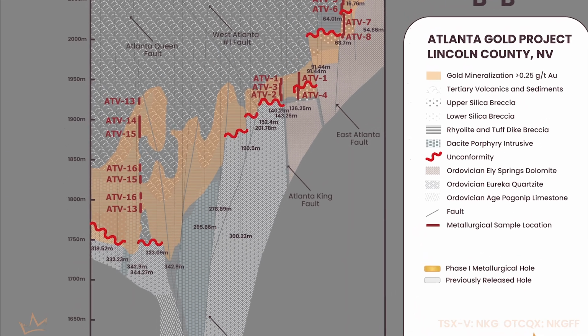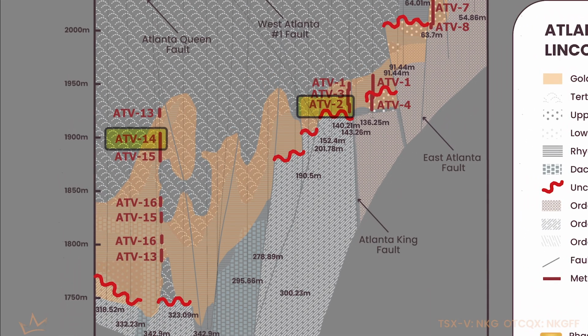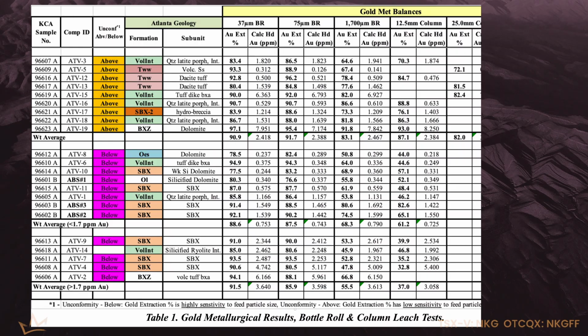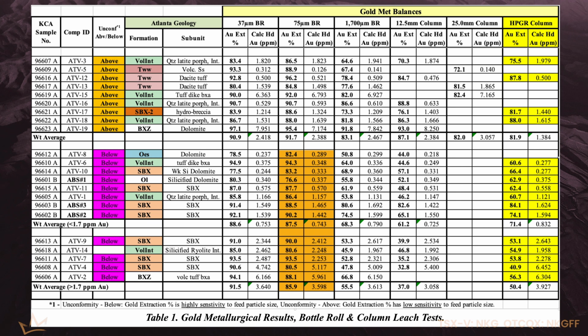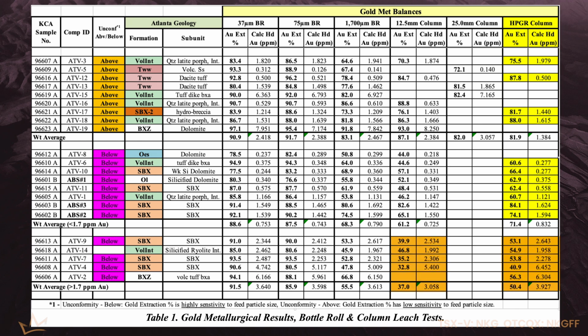When we looked at the silica breccias and one or two of the high silica composites that are slightly above the unconformity, we determined that they were amenable to milling just like the old operations had proved. Mid-80s to low 90s recovery at a conventional 200 mesh grind size. And one thing that we found out is that for the silica breccias, the higher grade material, the gold is more locked in the silica than it is as the grade drops.